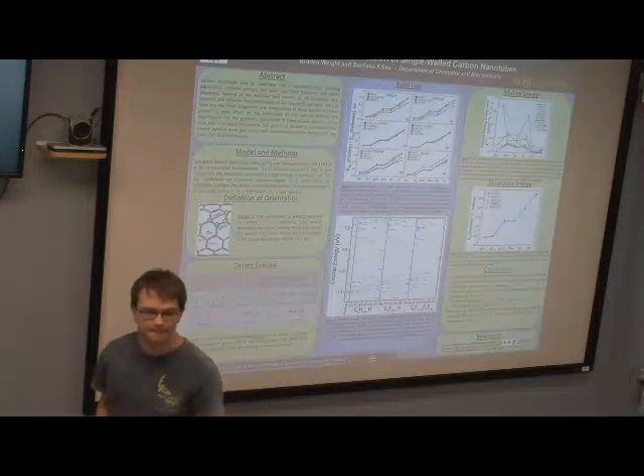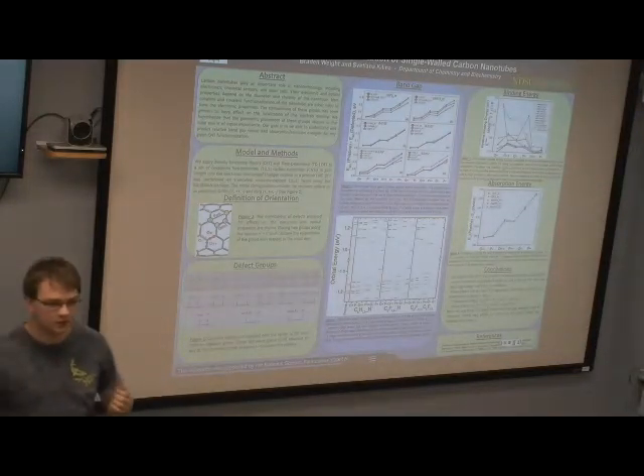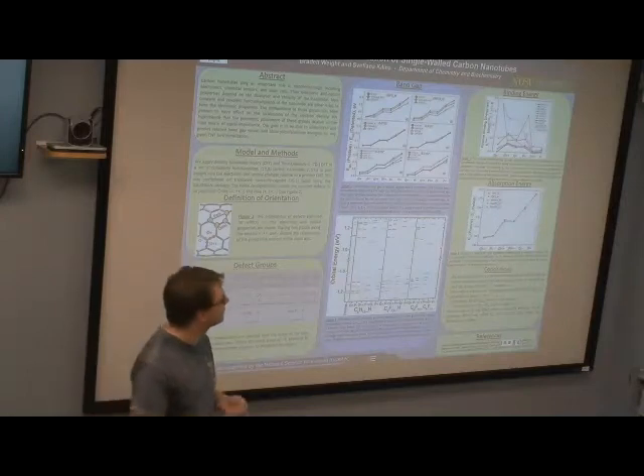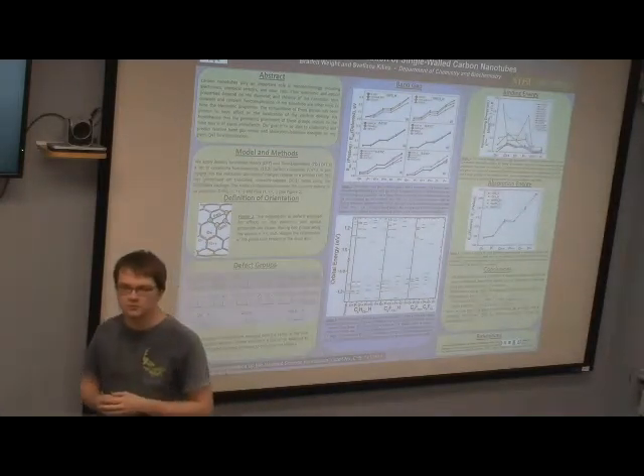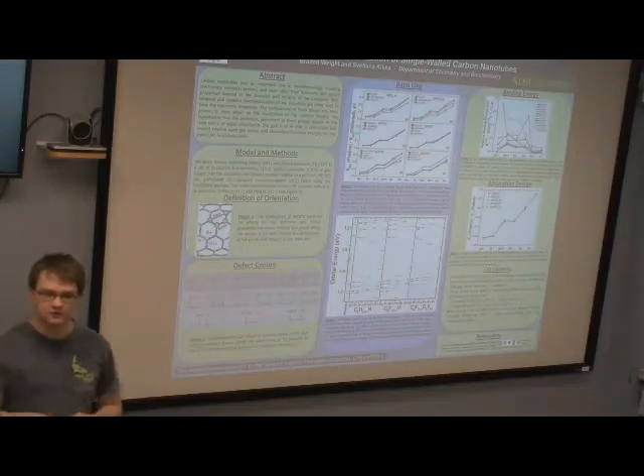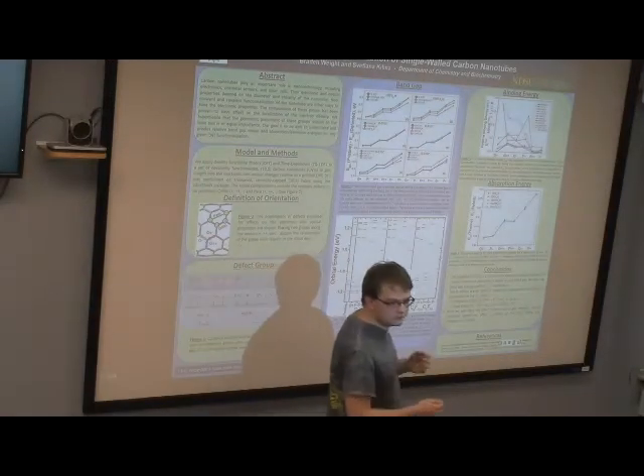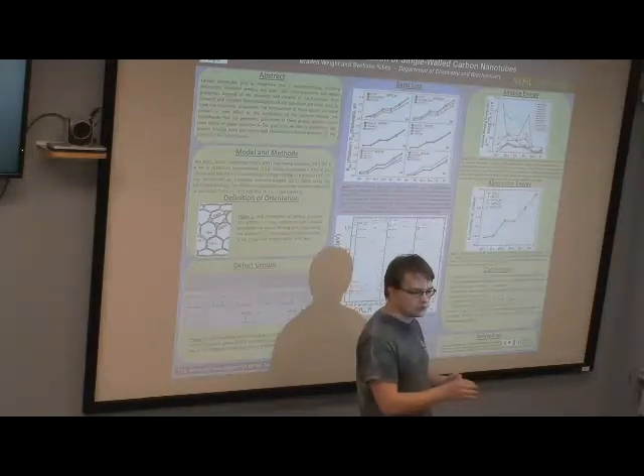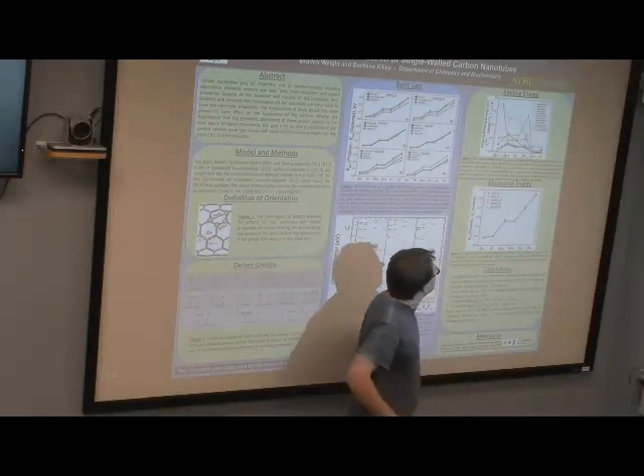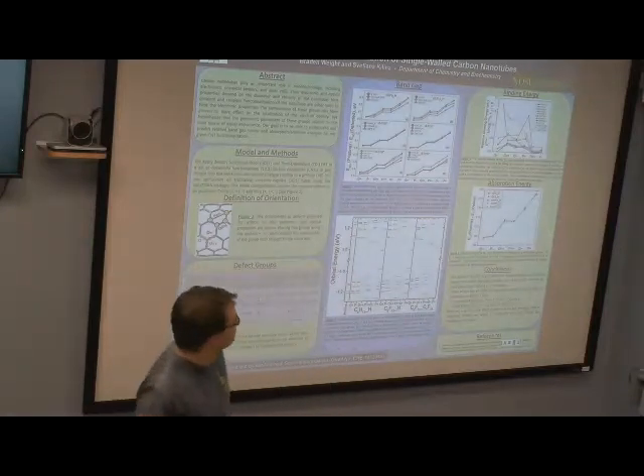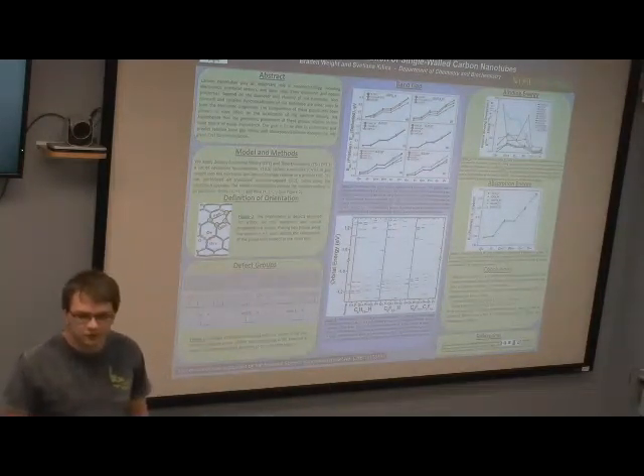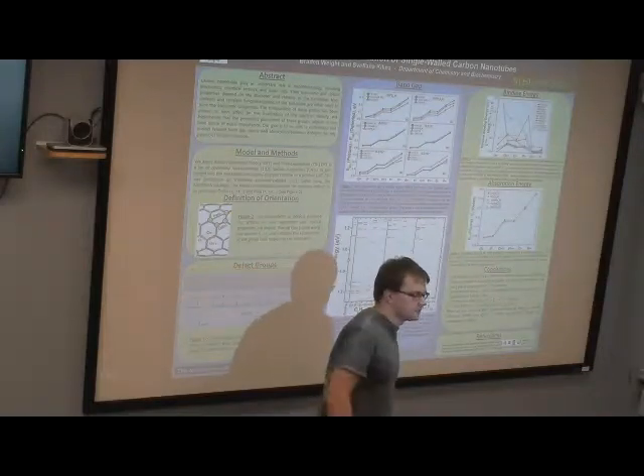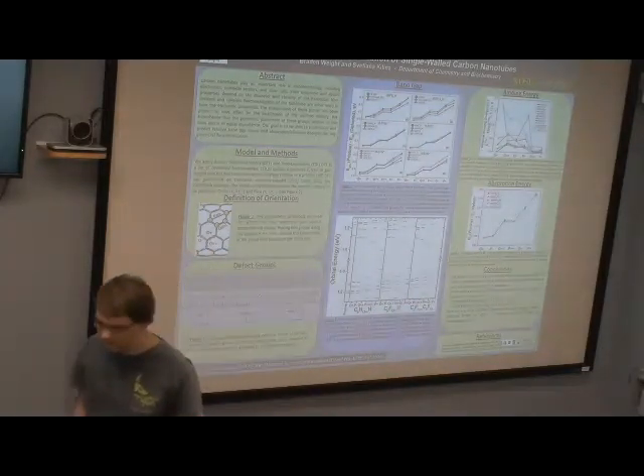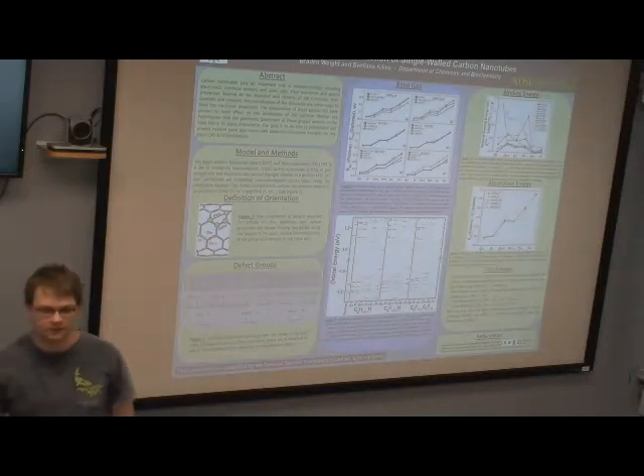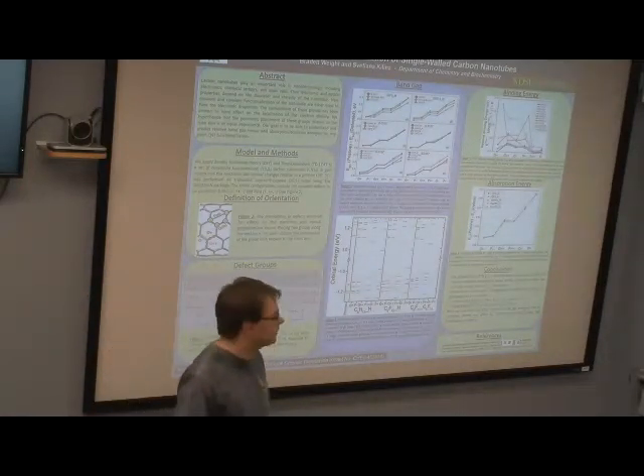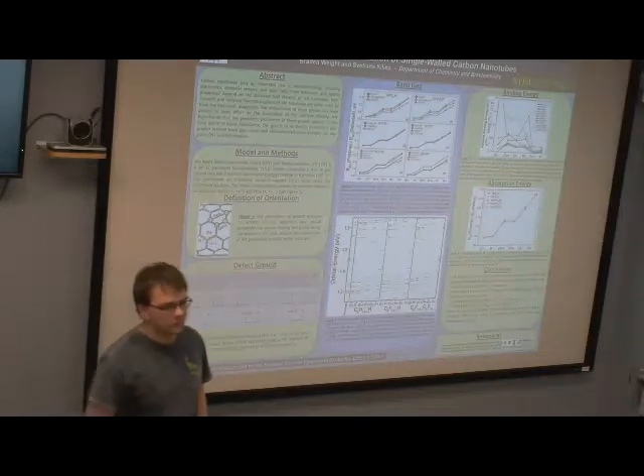And so I'll define the relative binding energy as the total energy of the system at a given defect, at indices 1 through 6, minus the minimum defect of those 6 orientations. And so that gives us something relative to each other with respect to orientation around the ring of this defect. So it's kind of a mess. Not 100% sure if there's a lot to interpret from it, because it's very sensitive. Many of my defects are very flexible and can adopt many different orientations in space with respect to the tube and with respect to each other.